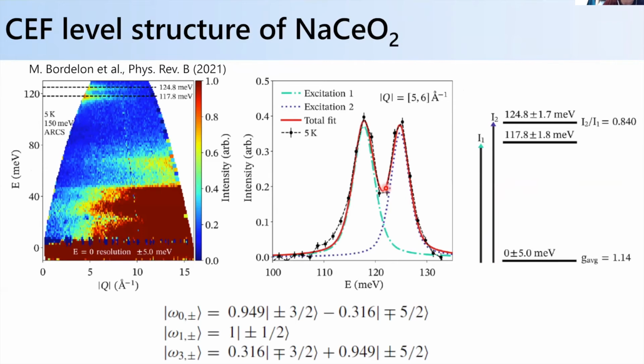However, in the single ion physics, we can fit the crystal field of this one. We can establish the crystal field scheme. Again, in this case, it's cerium 3+. We only see 2 excitations. Those are the 2 we should see. So we can fit the ground state, and it's well separated. The first excited state is again quite high. It's at near 120 millielectron volts.